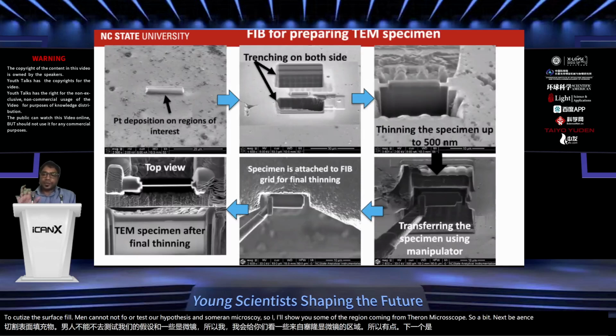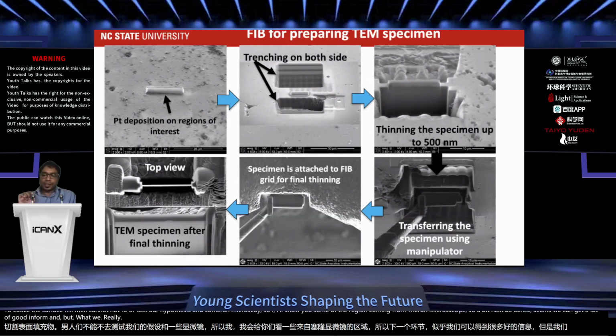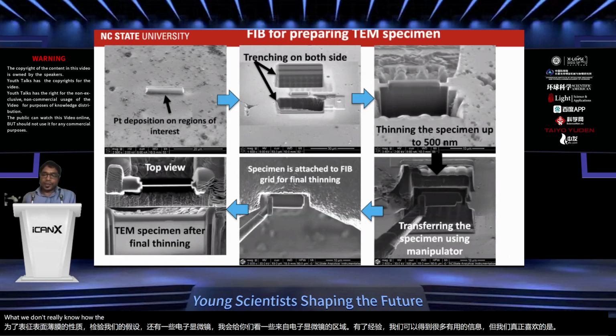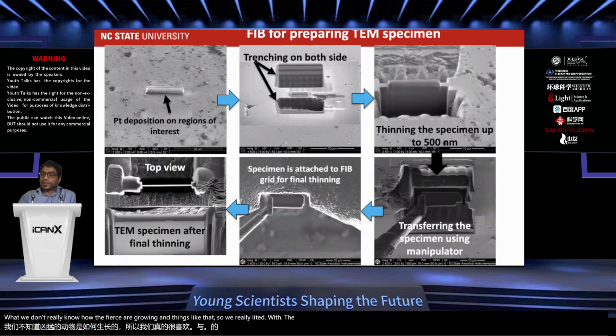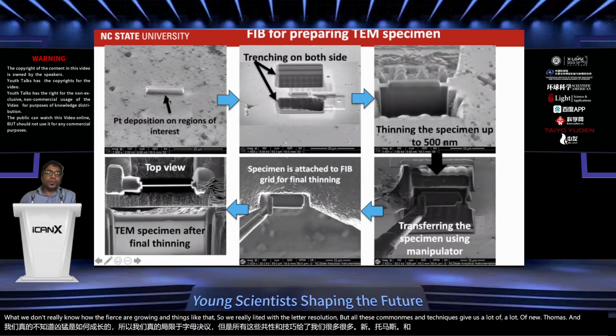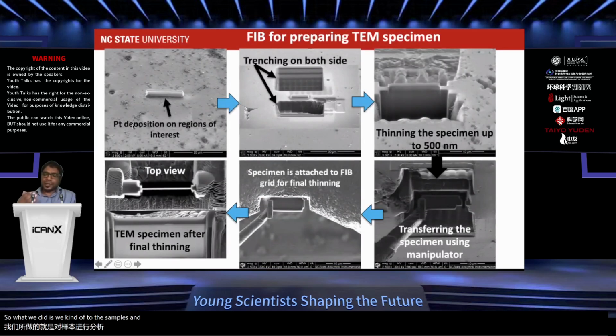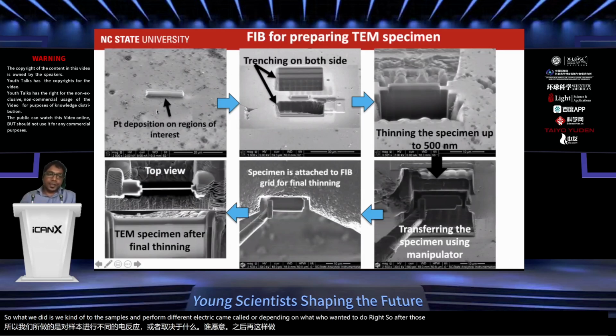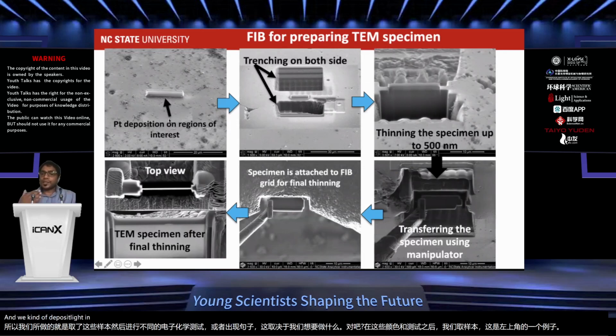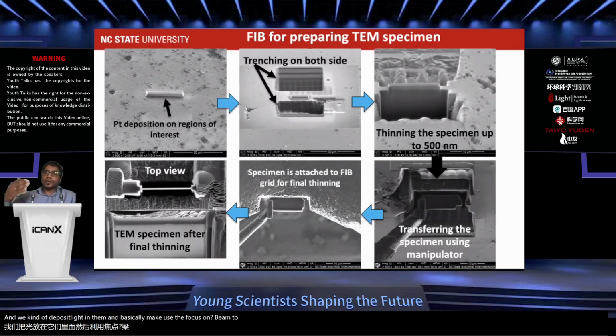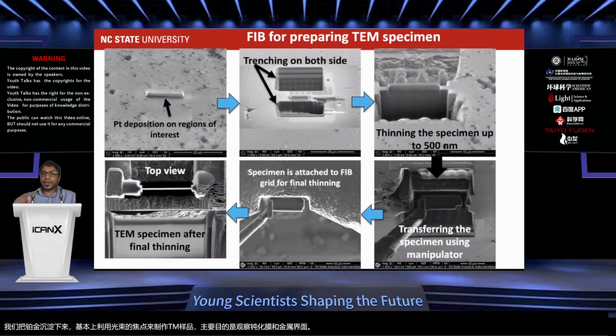With XPS and SIMS, we can get a lot of good information, but what we really lack is that we don't really know how the pits are growing and things like that. We are limited by the lateral resolution. But this combination of techniques gives us a lot of new information. So what we did is we took these samples and performed different electrochemical tests or immersion tests depending on what we wanted to do, right? After those corrosion tests, we take the sample. This is one example on the top leftmost, and we deposit platinum and use the focused ion beam to make a TEM sample out of it. The main purpose is to look at the passive film and metal interface and characterize how that passive film or surface films look, or how the pits look, right?